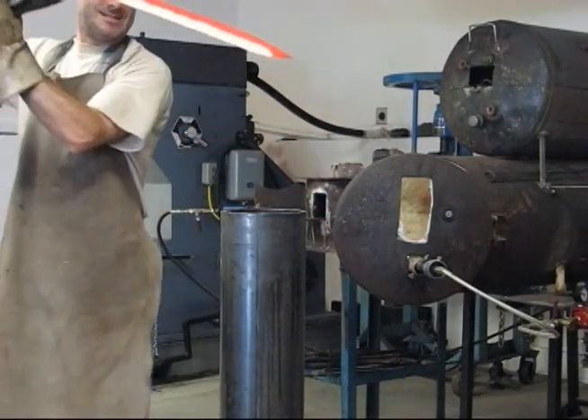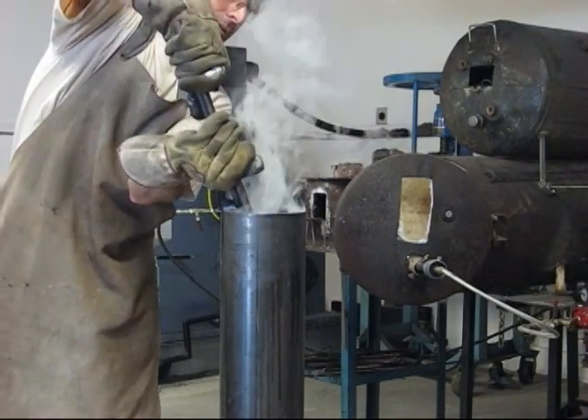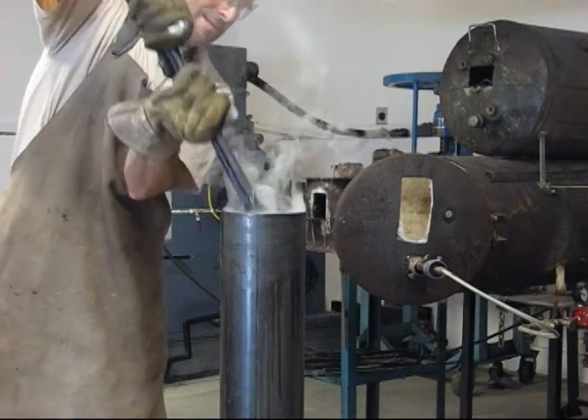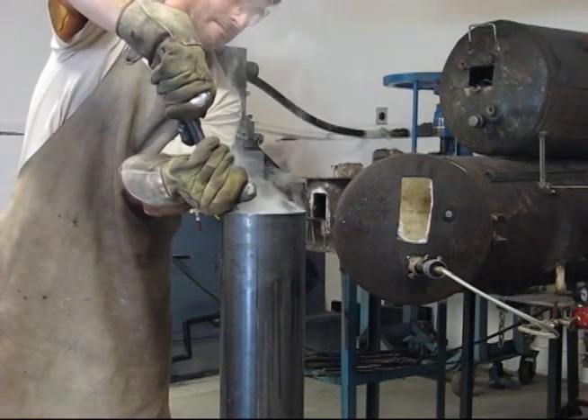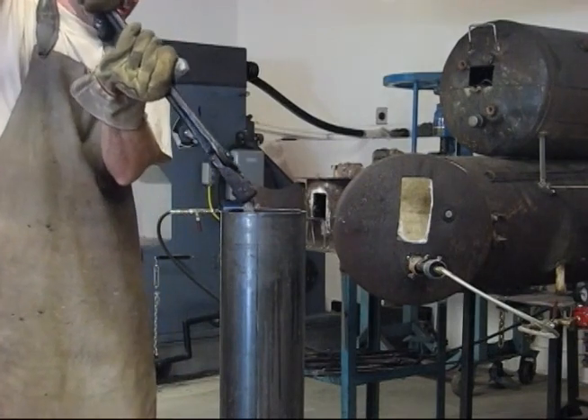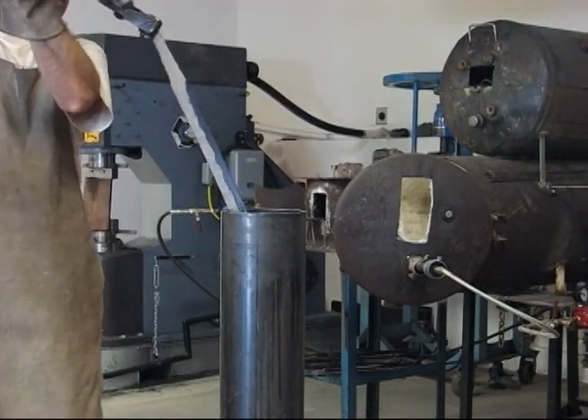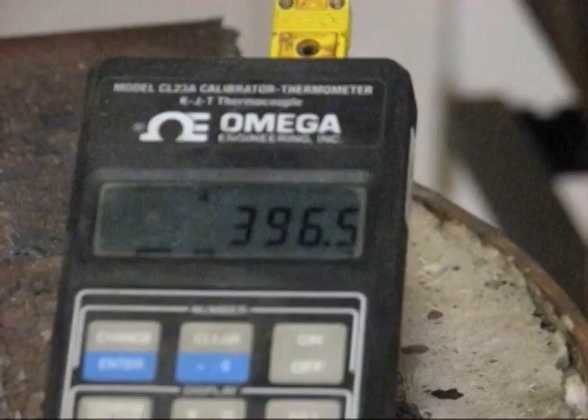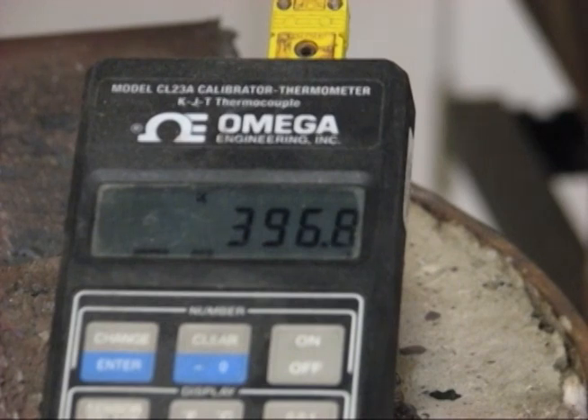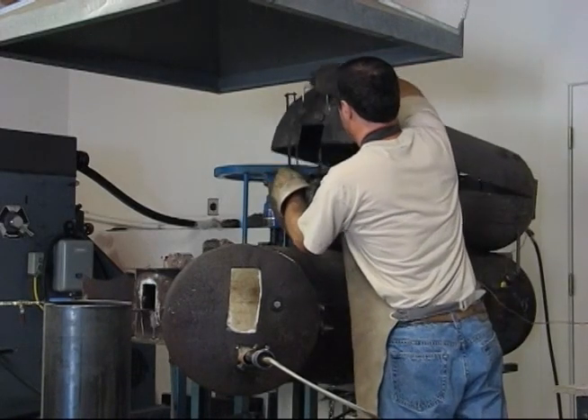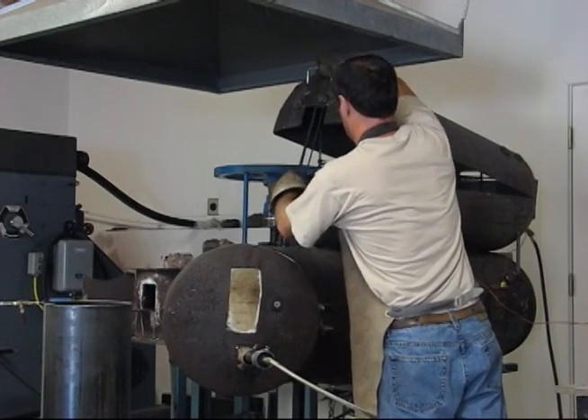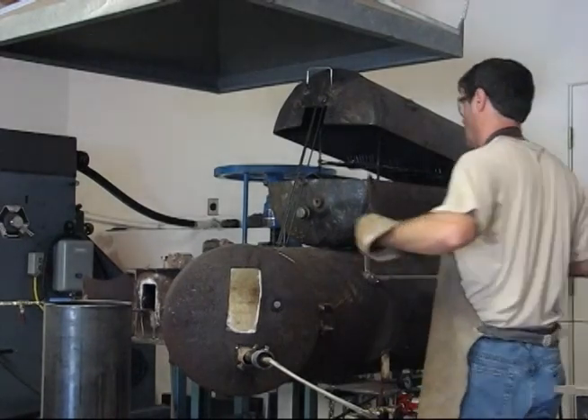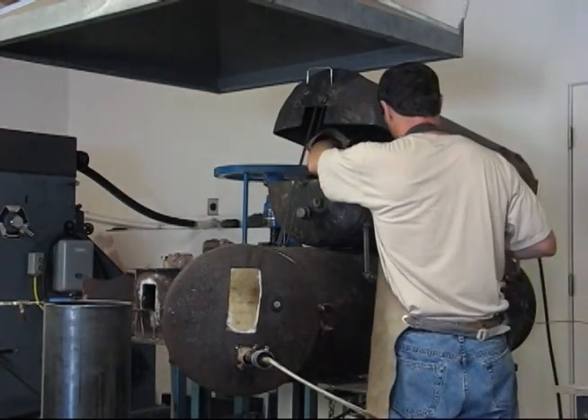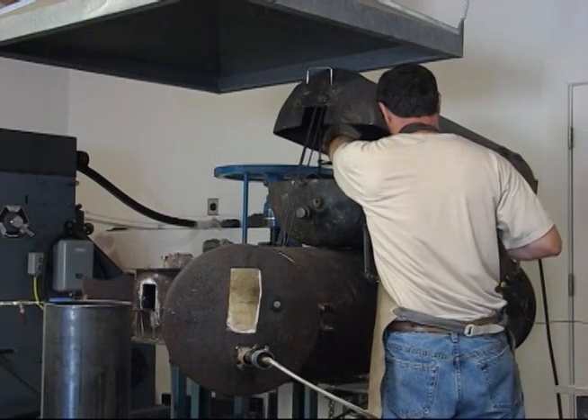Then it is submersed into the quench tank. The tempering oven has been kept at temperature all the while to avoid any time lapse between hardening and tempering. During tempering, the blade is heated up again to a temperature that will remove some brittleness from the edge, while leaving it hard enough to be functional. It's a compromise between edge retention and durability.